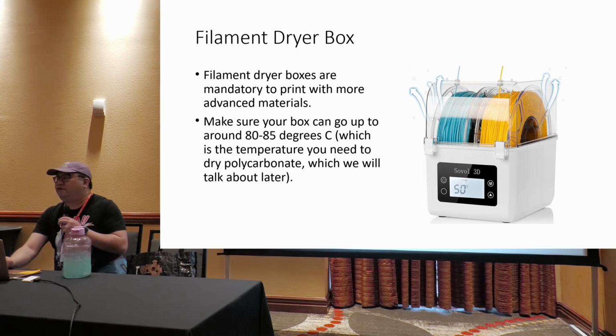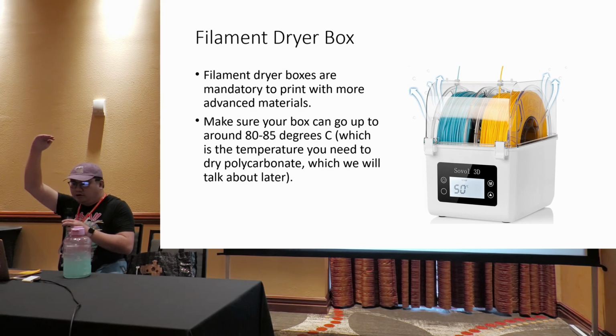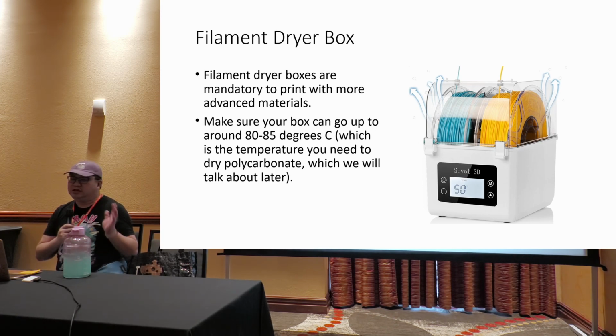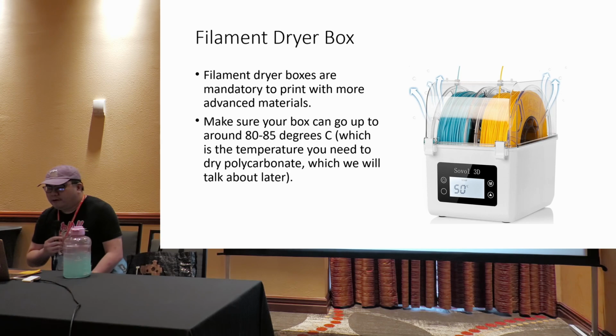Another thing you will need is a filament dryer box. I've got 2 very expensive boxes right now. They're stacked up on a shelf above my printers, but you don't need something super expensive. For the purposes of this panel, you only need a box that goes up to about 80 to 85 degrees Celsius. That temperature is what you need to dry polycarbonate, which is one of the materials that we're talking about today.